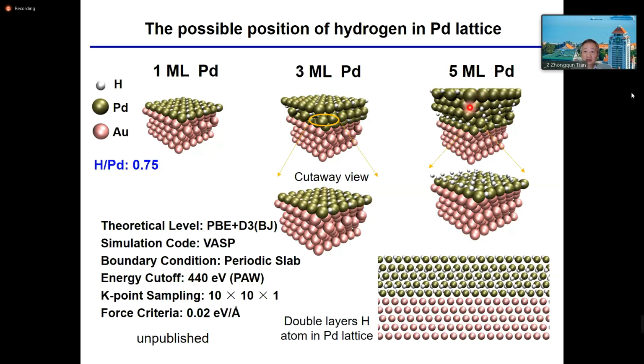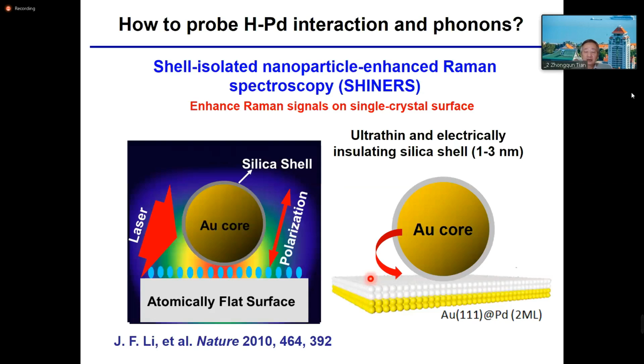However, if you change it to 5 monolayers, the situation is quite interesting. As you can see, in the first layer, hydrogen is up. In the second layer, hydrogen is down. So the hydrogen on these 2 layers is quite close, but between the first layer and the second top layer, hydrogen is separate. That provides some interesting modeling.